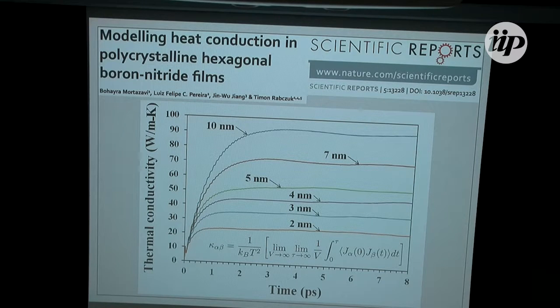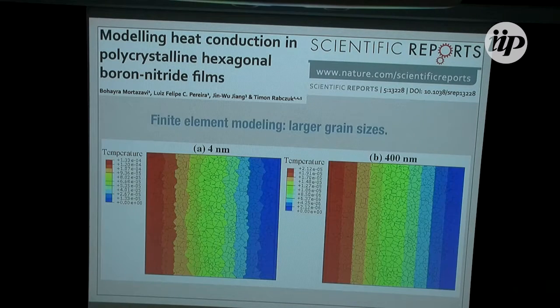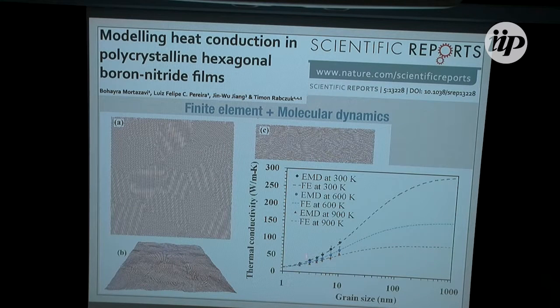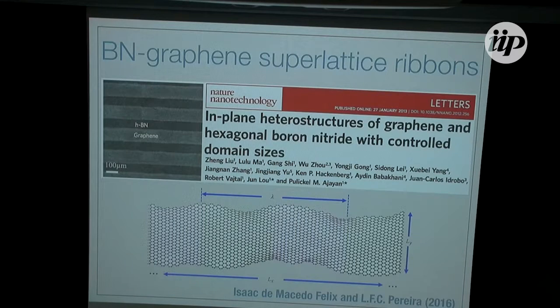If each patch is larger, the phonons can propagate longer within the patch. We mix this with some finite element modeling, because then we can predict the thermal conductivity for systems with much larger grain sizes than we could do in our simulations. The interesting thing here is that if you have grains of about 200 nanometers, the thermal conductivity of polycrystalline hBN is 90% of the thermal conductivity of pristine BN at 300K. So if you need a material with a high thermal conductivity, even if it's not monocrystalline, you just have to make your grains about 200 nanometers, which seems to be feasible, at least for this material.